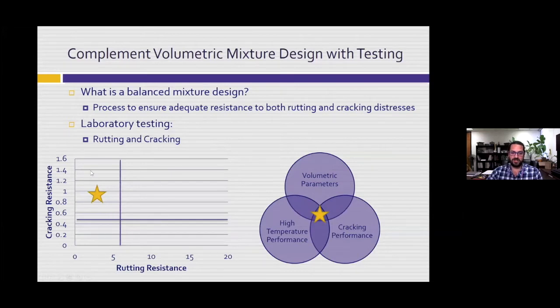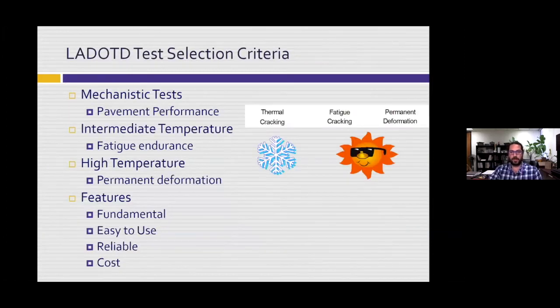And essentially what we do is we run a cracking test, we run a rutting test, and we make sure our mixtures fall into a quadrant that is going to give us both good rutting resistance and good cracking resistance. So in terms of our selection criteria, we wanted a mechanistic test, a test that could be used in our pavement design as well, because if we're going to be running laboratory testing and collecting the data, we'd like to be able to use it in more than one way. If it's a mechanistic or fundamental test, then we're able to use that in pavement design to help determine our asphalt layer thickness values.